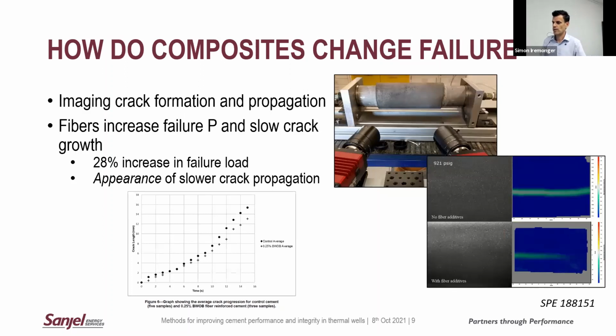And then we coupled this with direct image capture, so we're able to do high resolution imaging and direct strain mapping of that surface and actually directly follow the buildup of strain on that surface and follow where cracks initiate and propagate through the material. And the animation that's playing there in the bottom right corner is just showing how the strain is propagating through and we're getting a failure as a function of different pressure inside that casing, which is inducing obviously a hoop stress in the cement.